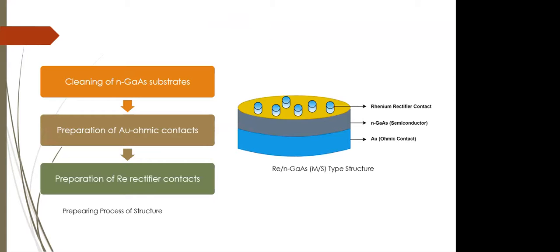Now I continue my presentation, the preparing process part, methodology. The ohmic contact, the MS contact shown in the figure has been prepared by following the steps shown on the left side of the slide diagram you can see. First, the N-type gallium arsenide substrates were cleaned with the cleaning method frequently used in the literature. Then the gold metal with high purity was deposited on the back surface of the N-type gallium arsenide substrate by thermal evaporation method. The thickness of the ohmic contact is 200 nanometers. For low resistivity, 450 degrees centigrade heat treatment has been applied for about 5 minutes.